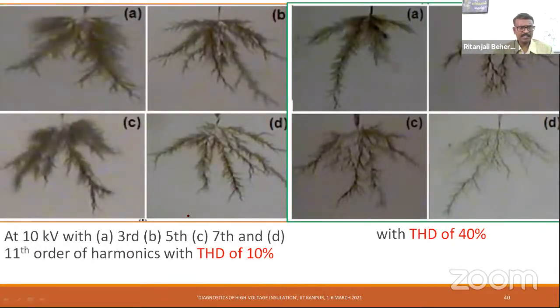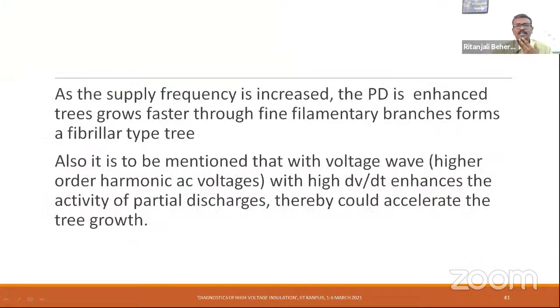Now, this is at 10 kV, with 3rd, 5th, 7th, and 11th order harmonics. The THD of 10% is given by this A, B, C, D, the first four, that is the four pictures on the left, and the four on the right give the THD of about 40%. The difference is only the THD. However, we can see that because of the harmonics present, more fine branches or fibrillar branches have been formed from tree-like trees. The reason could be that as the supply frequency is increased, the PD is enhanced and the tree grows faster through fine filamentary branches, and that forms more of a fibrillar type tree.